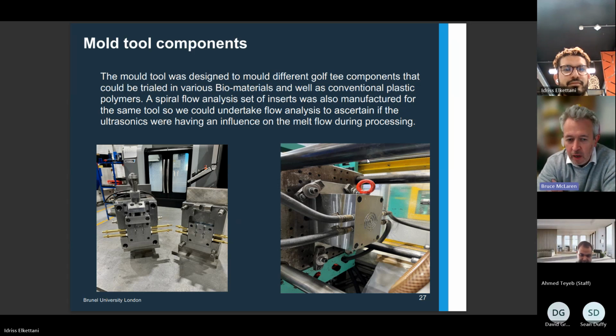And then again, we started off with the golf tee molds on the left-hand side, but then during the project, it was decided to make a spiral flow tool as well, just to really help with the analysis. Because what we're also starting to see is if we had the ultrasonics on or off, we could create a short molding. But then if we switched them the other way around, we then had a complete molding. So we were seeing a difference between having the ultrasonics off and on. So the spiral mold on the right that we made as well really helped with that analysis, and the results that we submitted into Brunel would impact.